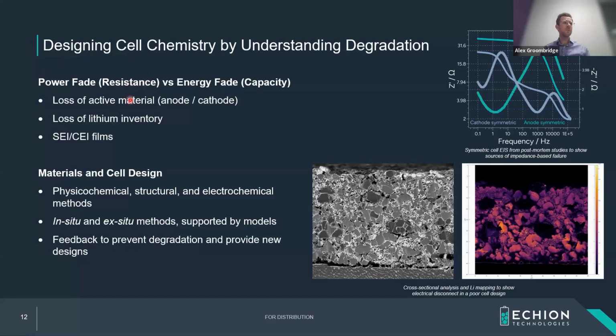When we think degradation at a very high level, this approximates to really two effects. One is power fade, so increase in resistance in a cell, and one is energy fade, a decrease of capacity in the cell. And these come from many different sources, but at a high level, that would be loss of active material, cathode degradation, forming rock salts, for example, or dissolution, loss of lithium inventory, or film formation.